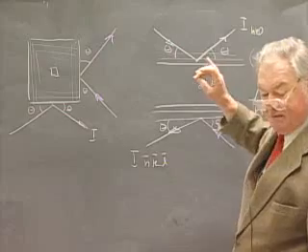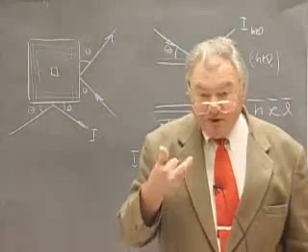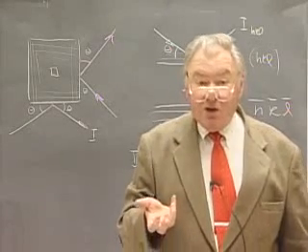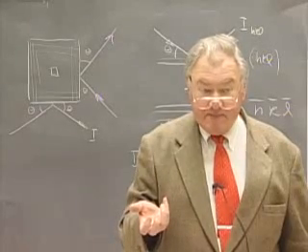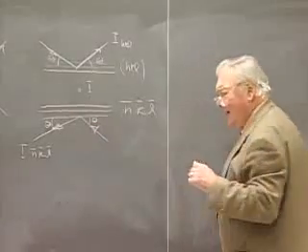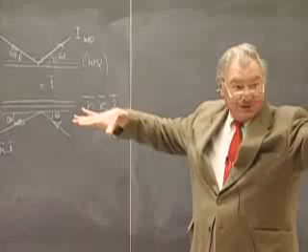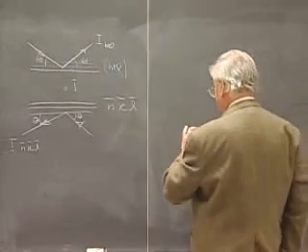So therefore, and I qualify this by saying, to a good approximation, the only point groups that you can determine and distinguish from one another by X-ray diffraction are the point groups that contain an inversion center. Almost, but not quite. If we look a little more closely at what is doing the scattering, it is not the Bragg planes. These are imaginary, shimmering, absolutely planar things that are constructs that we use to interpret the process called diffraction.